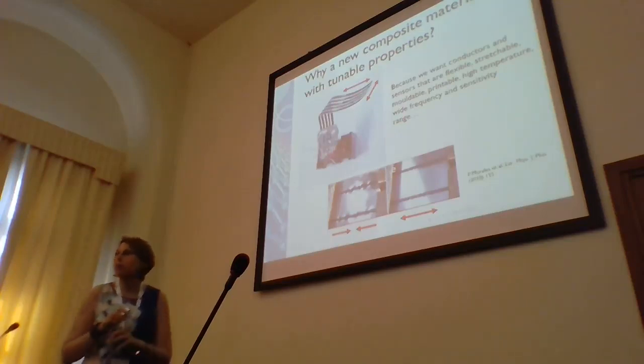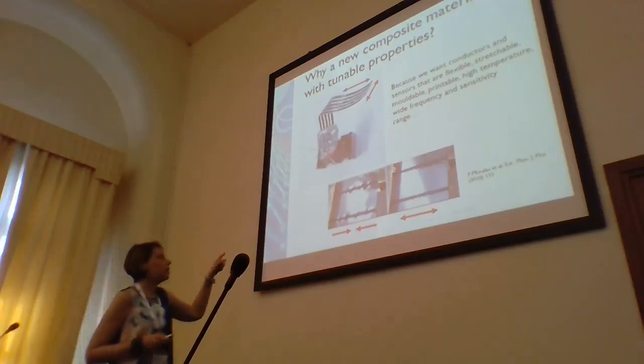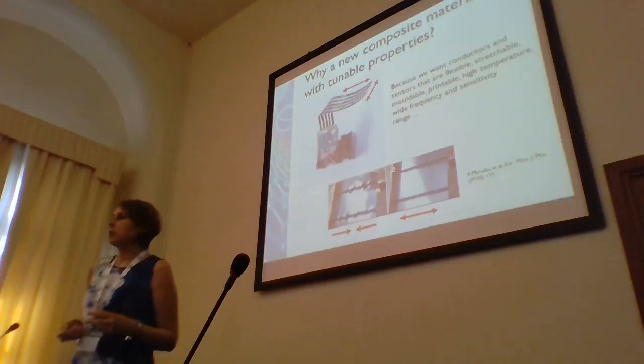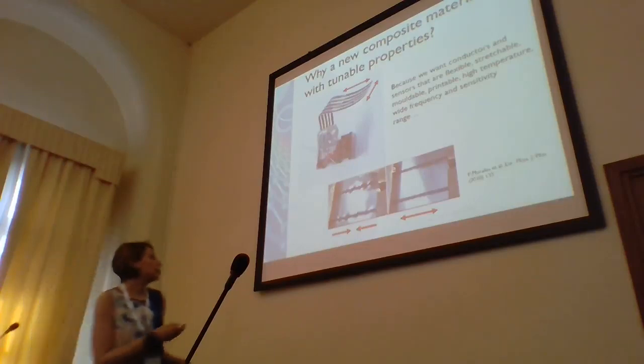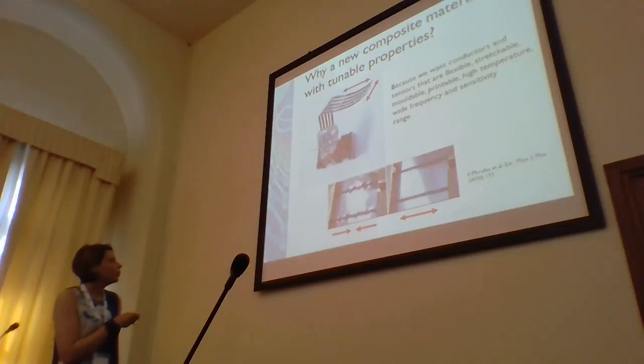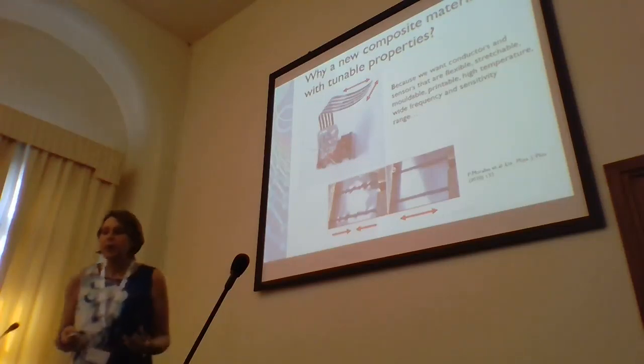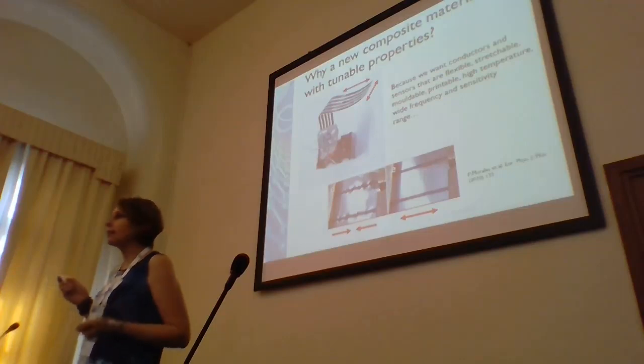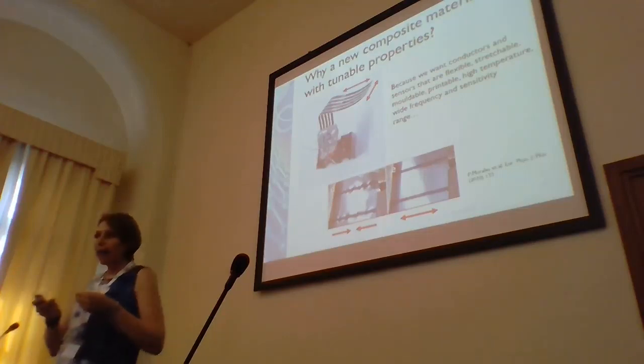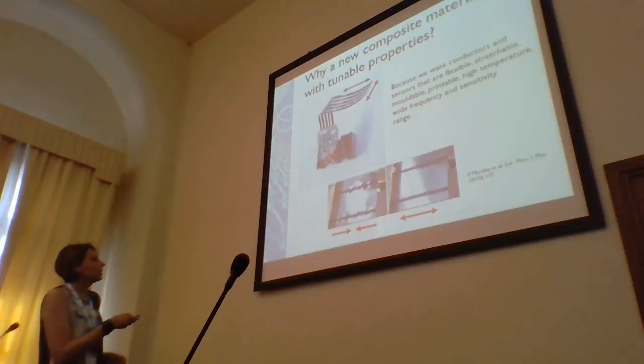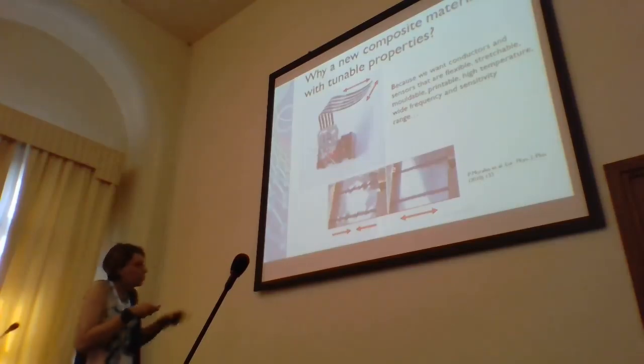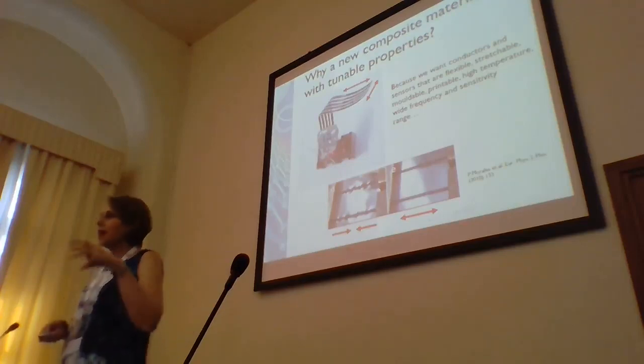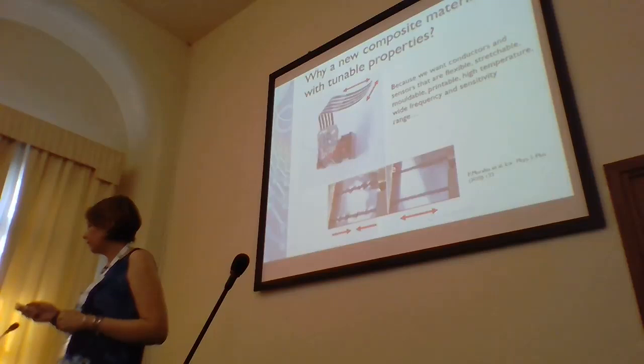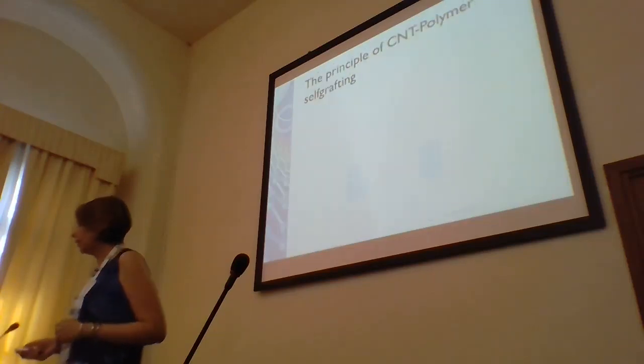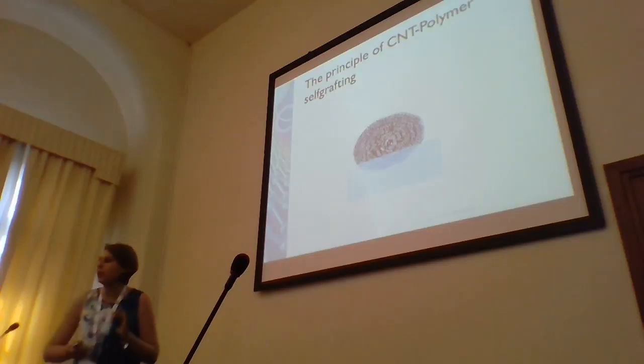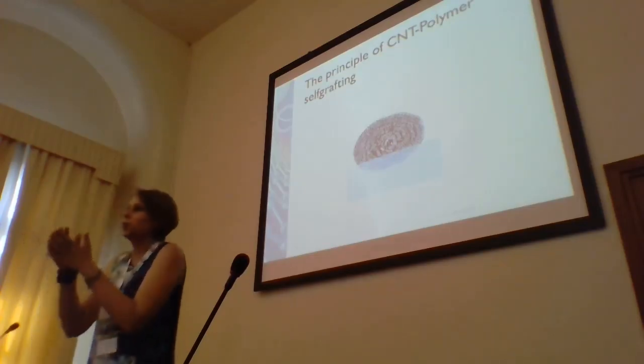This is a polymer film. In particular, this is a polyethylene film, about 20 microns, with 2 tracks of carbon nanotubes. You can see that a particular thing happens. This is self-grafting. You can see the relaxed and slightly stretched material, and you can see that the carbon nanotubes are inside and graft the polymer. Okay, what is the principle of CNT polymer self-grafting? I want to show you.